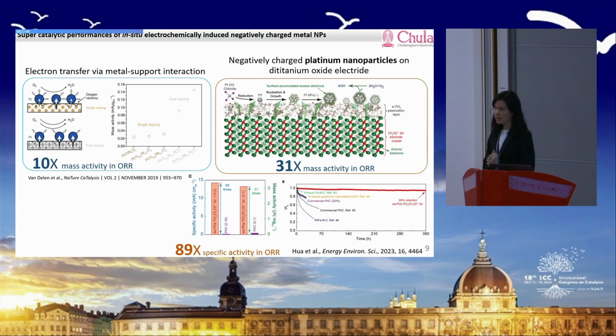In the field of heterogeneous catalysts, we may be familiar with electron transfer from support to the metal, right? Metal-support interaction is pretty much conventional. In this case, on the left side we have platinum on titanium dioxide, and then they add second elements to the titanium dioxide, and they are able to boost the oxygen reduction reaction activity by a 10 times increase of the mass activity of the platinum. That was in 2019 in Nature Catalysis.